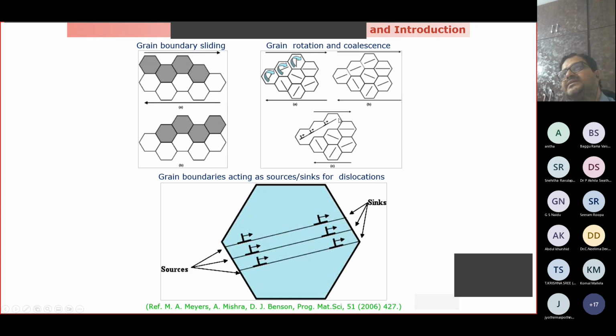But most of the insights to understand these mechanisms have come from molecular dynamic simulations, because to observe these things you really need high-end tools using very high resolution TEM and also the in-situ application of stress, and that is not a trivial task to do. Of course, some people have done it, but all they could do is to see the movement of dislocations only up to that point. Grain rotations and grain growth under in-situ TEM have not been observed. It's an extremely difficult task.